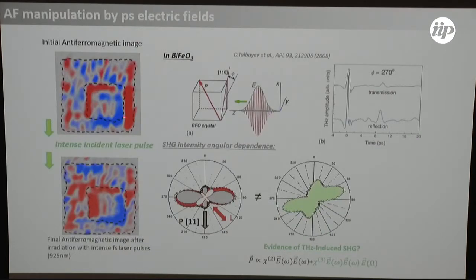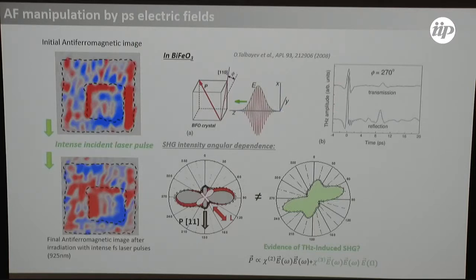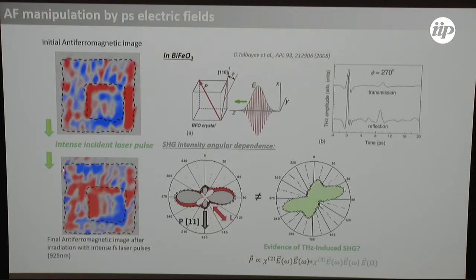Probably the most interesting thing is when we hit hard with the laser by increasing the femtosecond laser intensity. When a femtosecond laser hits a ferroelectric material it generates sharp rectification spikes in the terahertz or picosecond range. These spikes produce a magnetoelectric-type field at a frequency in the terahertz range, which is kind of resonant with the antiferromagnetic order. By just changing the incident laser pulse intensity, we can completely change the antiferromagnetic domains without touching the ferroelectric ones. This is proof that you can optically, at the 100 femtosecond timescale, address the antiferromagnetic order in this compound.